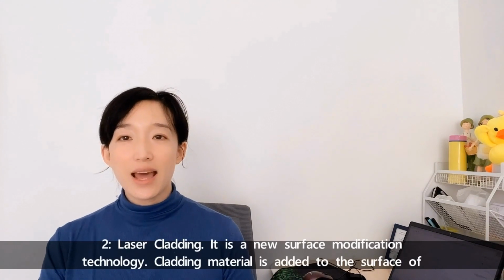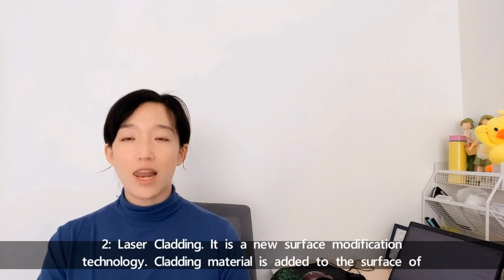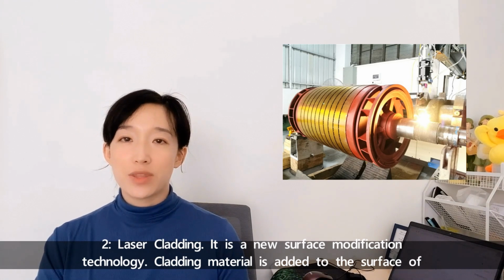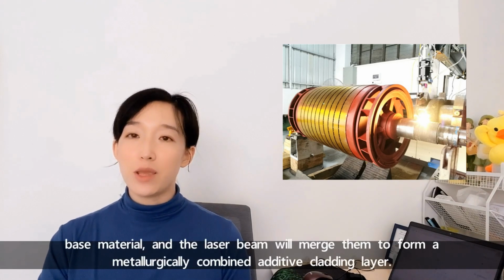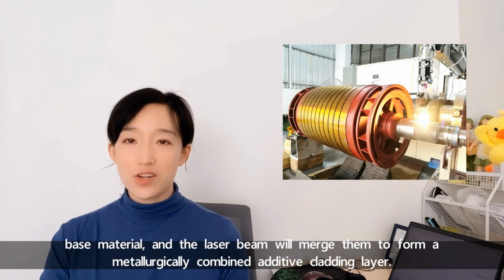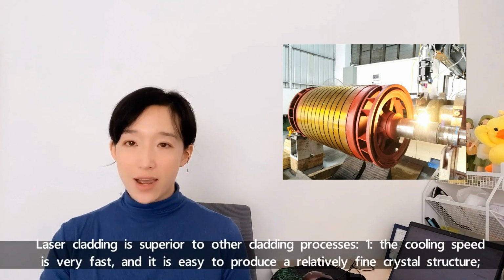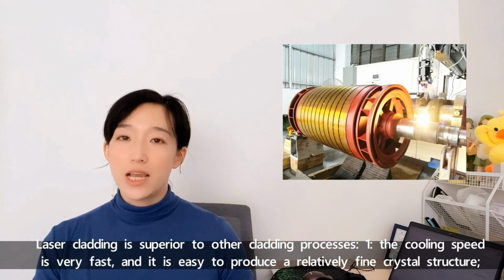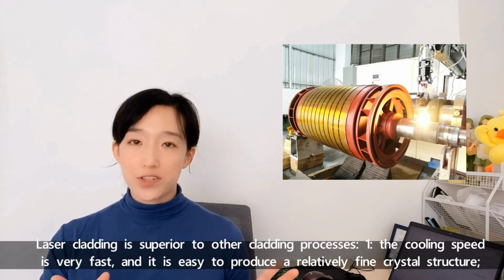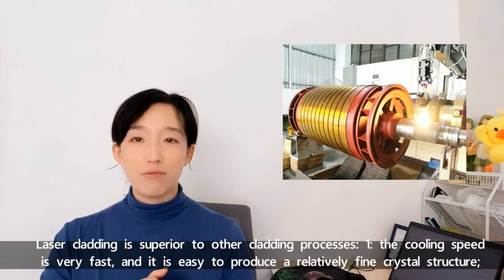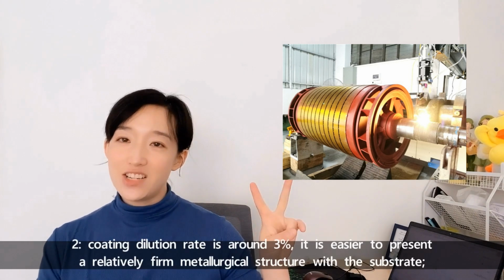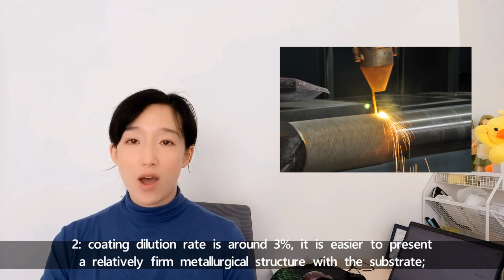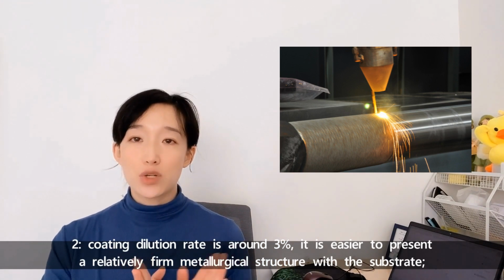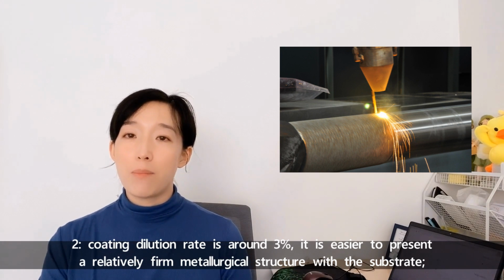Number two, laser cladding is a new surface modification technology. Cladding material is added to the surface of base material, and the laser beam will merge them to form a metallurgically combined additive cladding layer. Laser cladding is superior to other cladding processes. First, the cooling speed is very fast, and it's easy to produce a relatively fine crystal structure. Second, coating dilution rate is around 3%. It's easier to present a relatively firm metallurgical structure with the substrate.